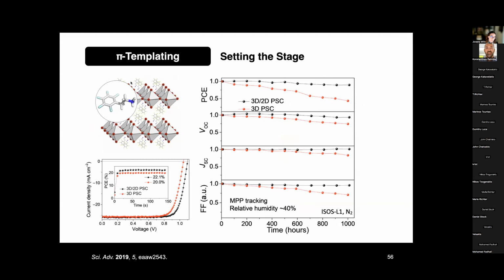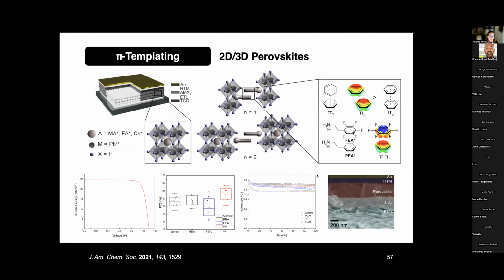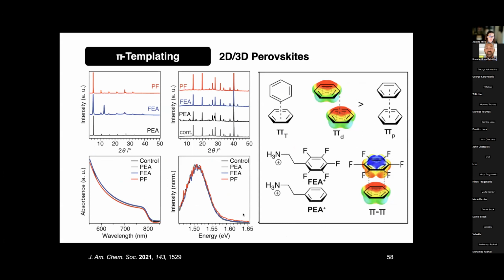Now, using such a system in a one-to-one mixture with its non-fluorinated analog enables maintaining this stabilization factor, while at the same time further enhancing the performance of these materials in conventional solar cell architectures, here illustrated by this cross-section, where these two-dimensional overlayers were applied at the interface between the three-dimensional perovskite absorber and the corresponding hole transporting material, which was also associated with the capacity of these systems, despite the formation of these well-defined two-dimensional structures, to maintain the resulting optoelectronic characteristics, which are very beneficial and should not be compromised.